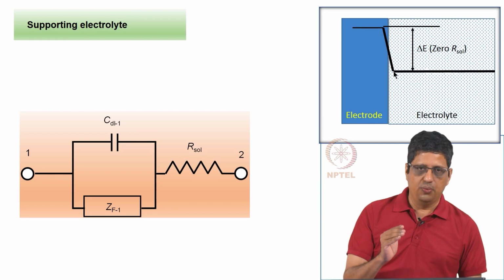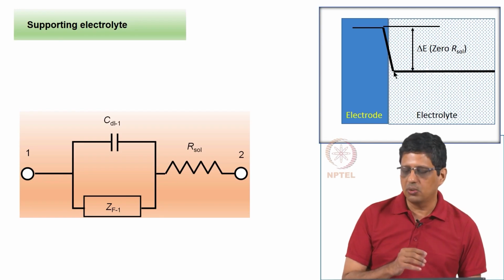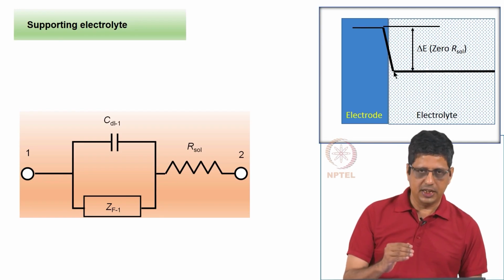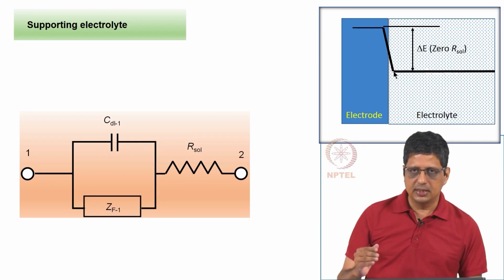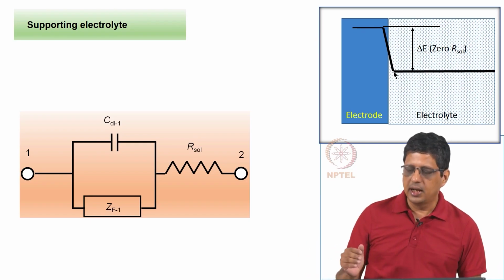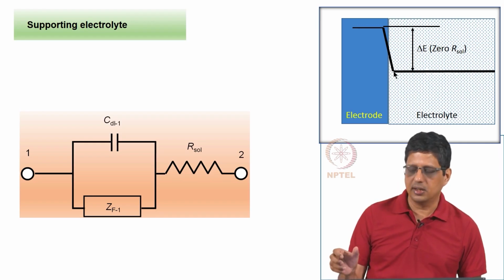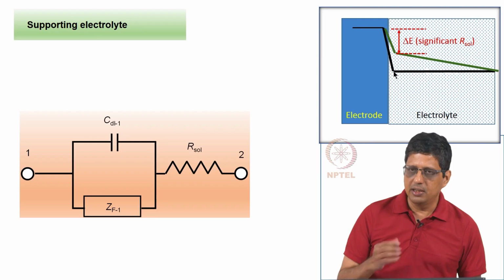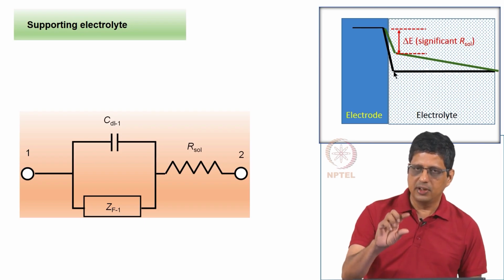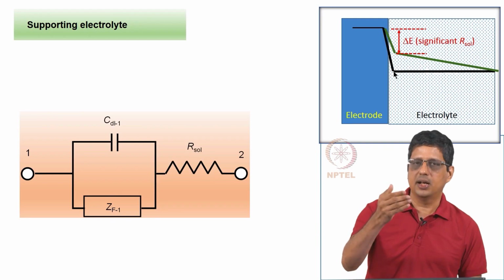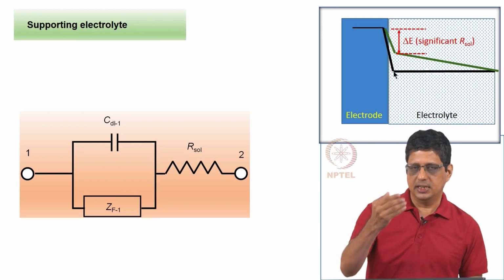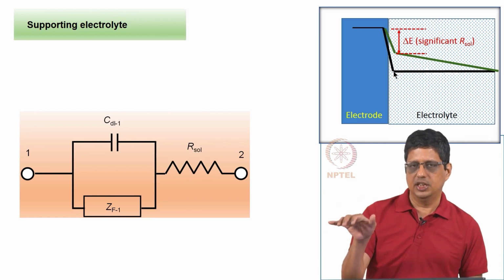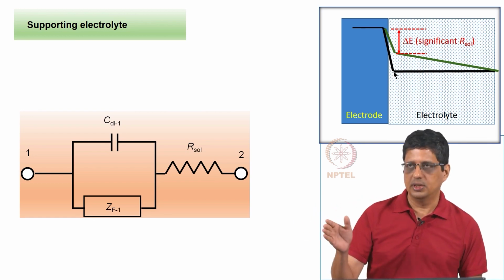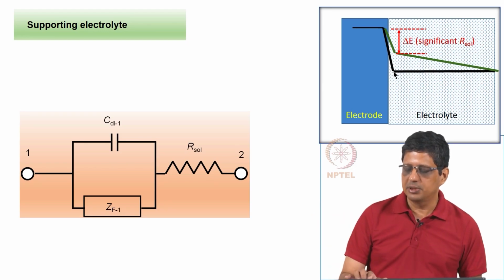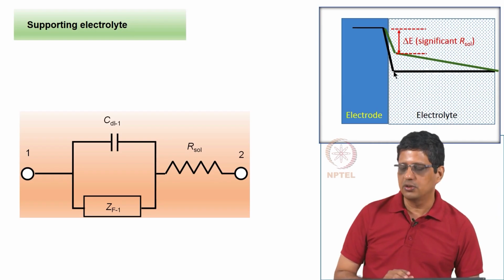If the conductivity is low, if it is just water with a little bit of salt, millimolar or micromolar of salt, then when you have a reaction that you study, current passes through this interface, current also passes through the electrolyte and a significant potential drop will occur across the electrolyte. Whatever we imagine that we are applying, we are changing the potential, the additional potential is applied across this electrode. We imagine that it is occurring across the electrode, but a significant change may occur across, or between, the two electrodes in the system. So, this is a description of how the potential will look if we have high solution resistance.